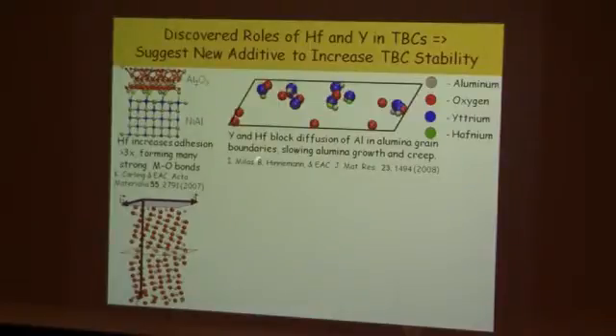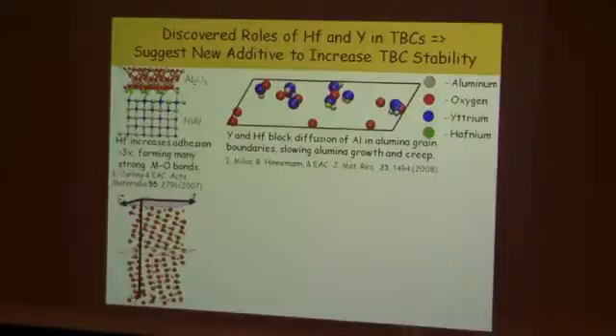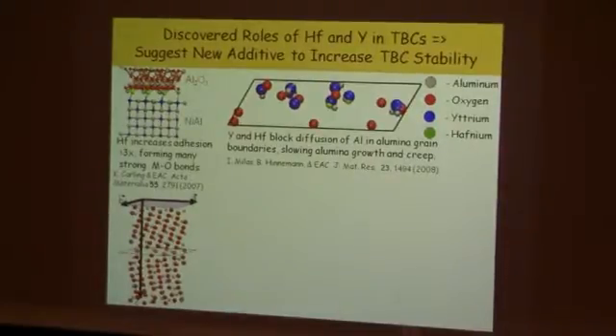And what we were able to discover is that another thing that hafnium and yttrium can do is to block transport of aluminum in the alumina to slow down the growth, and something called creep that I don't have time to talk about. But it's something which, again, leads to failure. So the idea is that hafnium and yttrium are these big lumbering metal atoms that essentially sit in sites that frustrate the aluminum so that the aluminum can't go through the alumina to make more oxide. And so it stops the growth. And that's also really important.